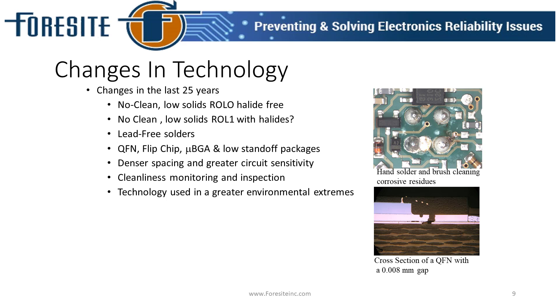With components trapping these fluxes where they're not allowing them to transition in temperature — because they're so tight to the board surface — we see the effect of the residue growing dendrites and shorting underneath the package itself, even though everything else on the board is fully functional.